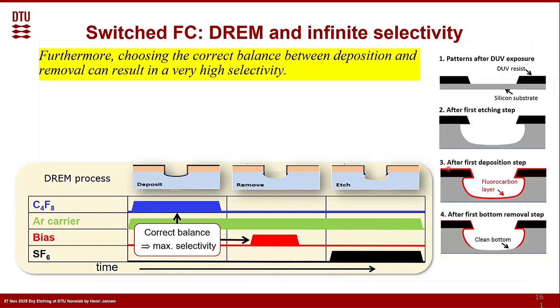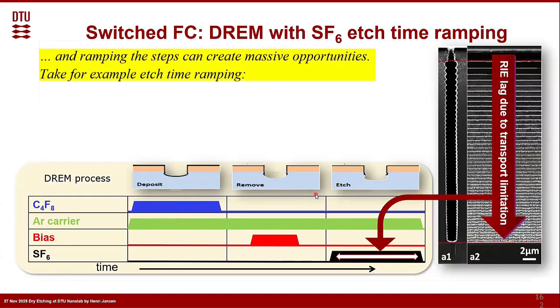That means that at the top there's a little bit more, and when you etch with the ions, the bottom will be freed earlier, whereas there's still something on top. So it could even be that instead of a high selectivity or infinity, your bottom is still etching, whereas on top it is even growing. Those are, of course, very unique situations. Normally, you're already happy that you have a very high selectivity caused by this. But there's another thing which is really nice that we can use, which is that we can increase the etch time.